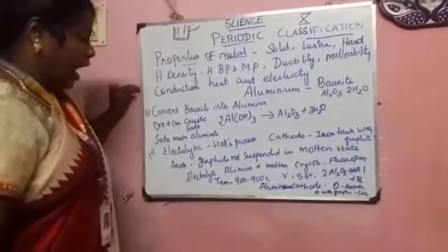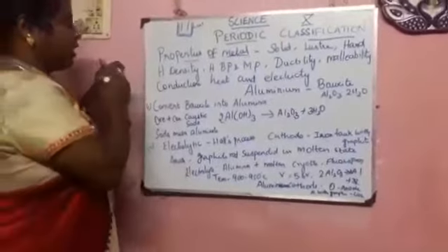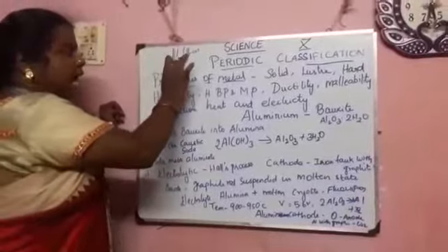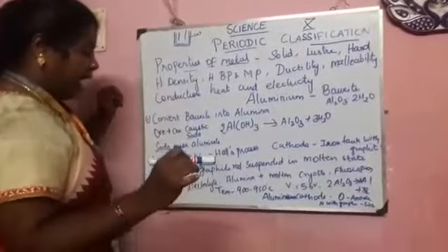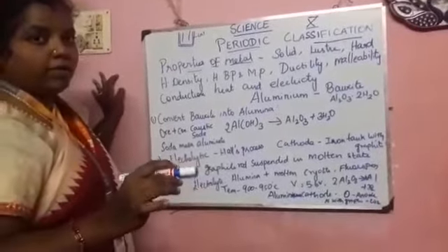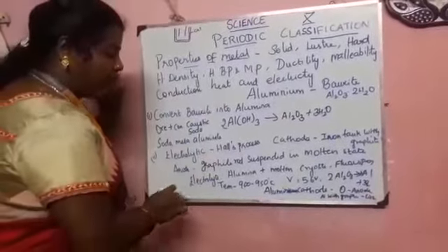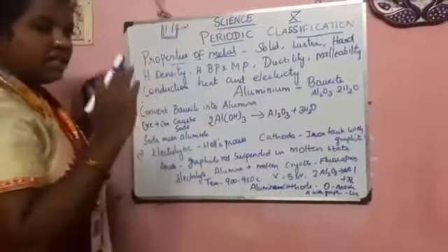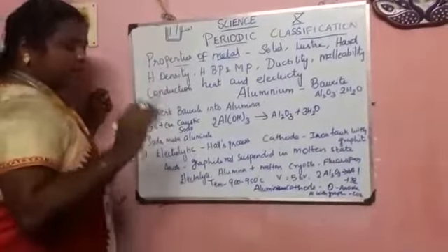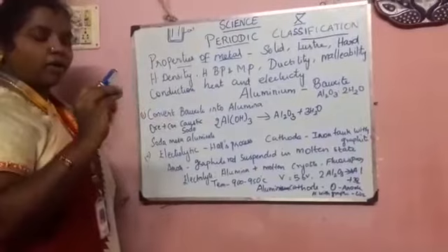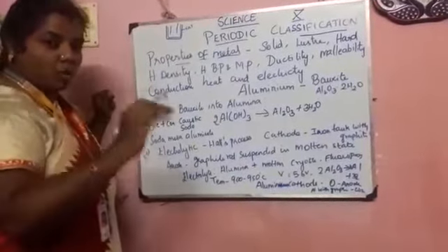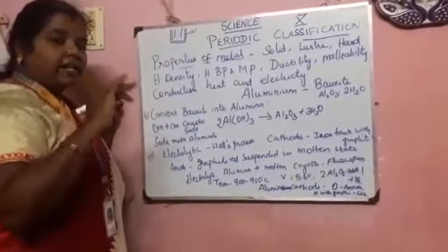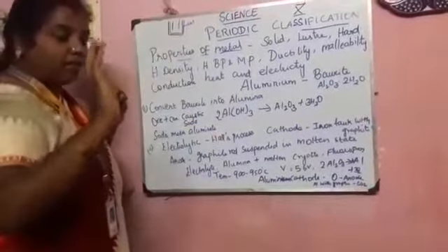Next, a graphite rod is suspended, meaning we have inserted it over the tank. It is the anode, also made of graphite. Next, the electrolyte. Usually the electrolyte is in a molten state. Here we have alumina mixed with molten cryolite and fluorspar. This mixture is taken. Then we apply a voltage of 5 to 6 volts and maintain the temperature at 900 to 950 degrees Celsius.